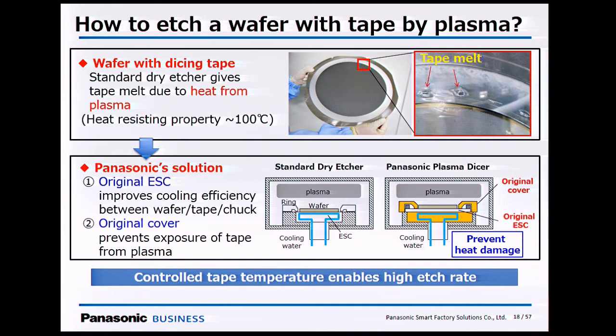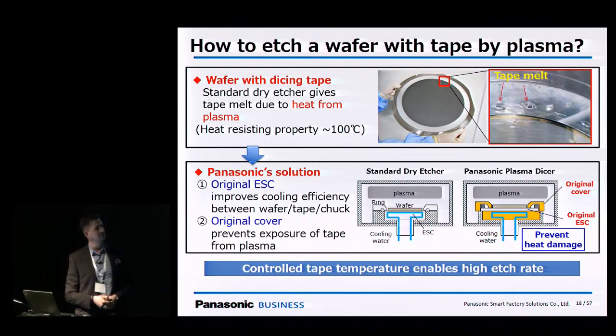So because we dice on a conventional dicing frame and tape, we need to make sure that the temperature is controlled so that we don't see any tape melt, like in the top right. Basically, we never see that thanks to our design. Two aspects. So underneath we have an electrostatic chuck, which is cooled to maintain 50 degrees Celsius dicing temperature, and also our patented covering design. So it's designed to the same size as the wafer, so that only the wafer is exposed to plasma, and this shields the edge of the dicing tape and frame.